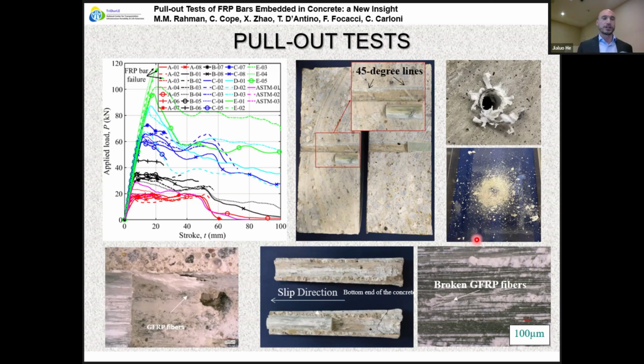So we did a little bit of analysis. These are all the results for all the bonded lengths. In the first color here, you also see the curves of the ASTM. So basically they work the same way. And if you see these two white lines, as you groove the bar, you remove the carbon wrap that is around the bar.